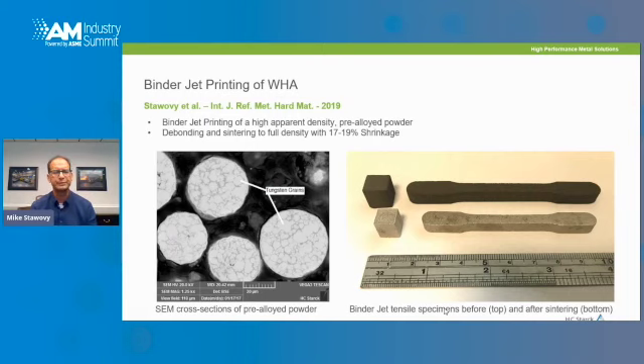We developed a specific pre-alloyed tungsten heavy alloy powder that is suitable for binder jet printing. With the binder jet printing, you can see some tensile specimens that we printed in the right-hand side photo. The top bar, the tensile bar, is in the as-printed condition, and then you see that there is some sintering shrinkage that occurs in the tensile specimen just underneath it. In this case, we're able to produce full density material that shrinks about 17 to 19%.